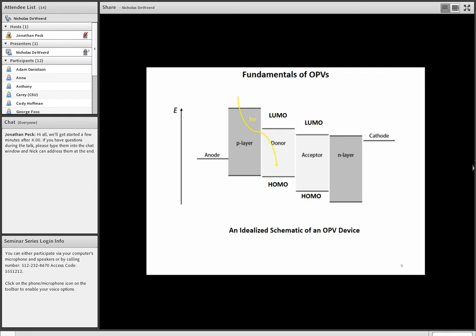So incident light comes in and excites what we would consider the HOMO of the donor molecule, and that causes an electron to be excited into the LUMO of the donor, at which point it becomes an exciton, an electron-hole pair. And then if the conditions for the device are correct, meaning the morphology is the way it's supposed to be, and the device structure and energy levels overlap correctly, the electron will be delocalized through the acceptor and then out through the cathode material, and then the hole will be similarly delocalized to the anode.